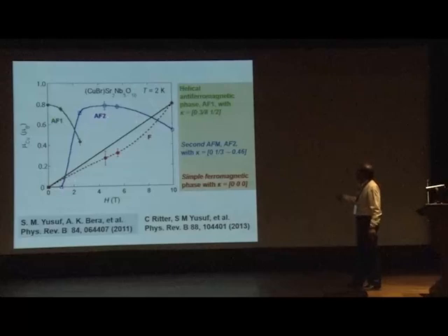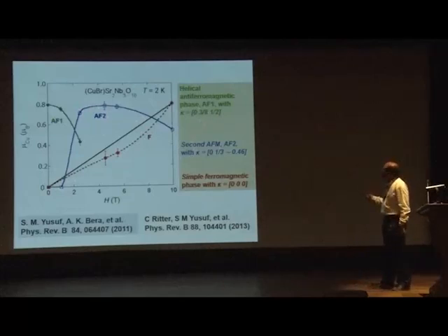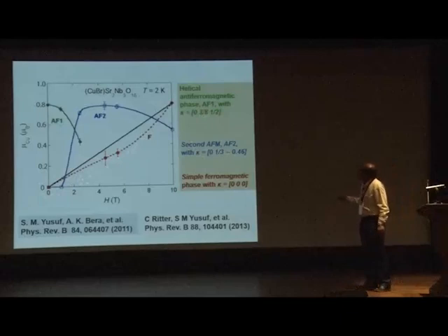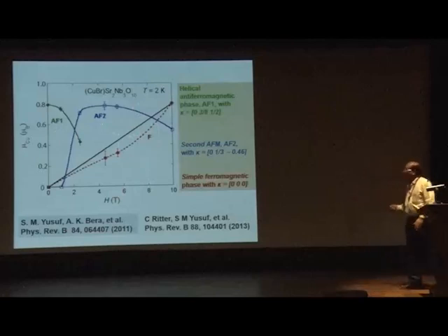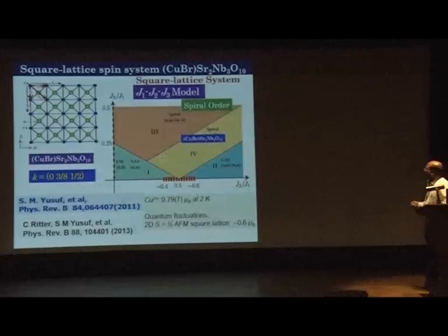What is the difference in this antiferromagnetic phase 2 is that this k vector, the magnetic propagation vector, changes from this to this. And over and above, we do get another phase, that is the ferromagnetic phase. So it is the coexistence of this antiferromagnetic 1 going to antiferromagnetic 2, and also the ferromagnetic phase. So this kind of beautiful phase diagram we could draw by doing experiments under magnetic field.